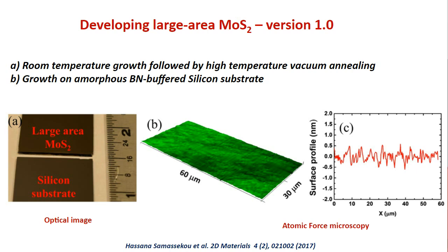So the first assessment we did was the surface, which is shown using AFM, atomic force microscopy. It looked really smooth. We also did X-ray diffraction. We did find the X-ray diffraction peak for MoS2. So our first check was really good. That means, oh, we have an MoS2 film, which is large area, right? So that is already a building block. It looks like we have done something in that direction that could be useful.